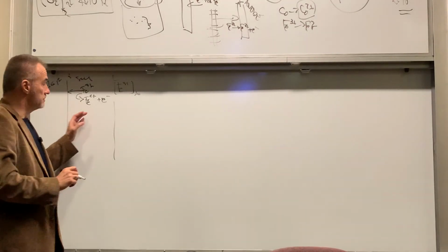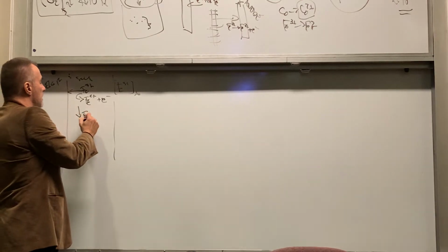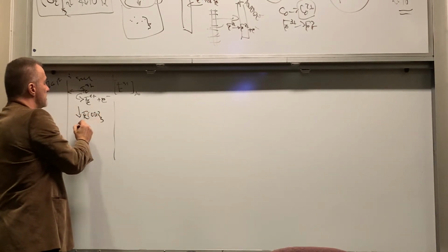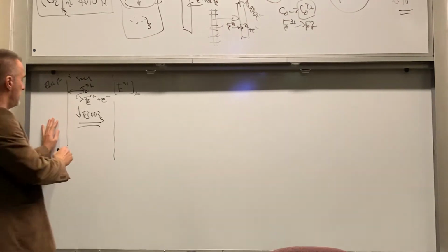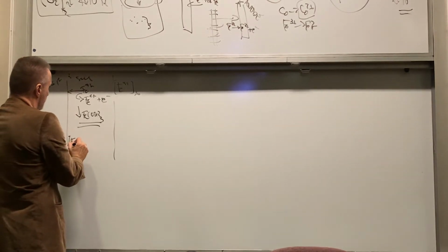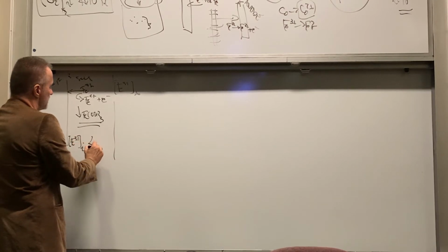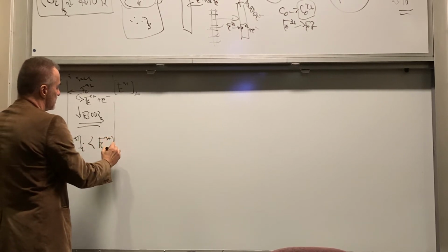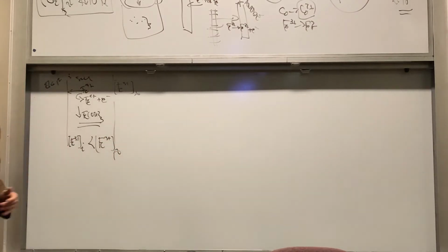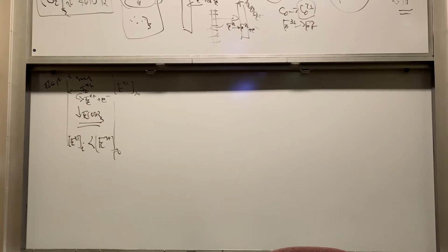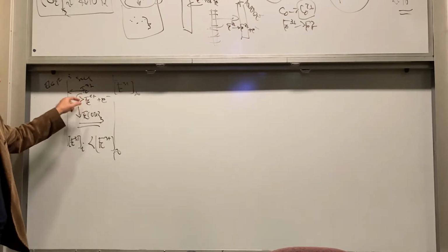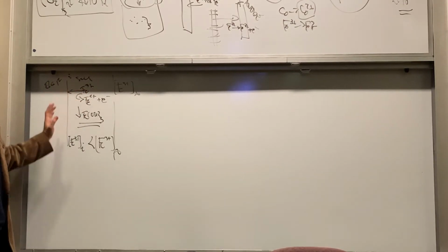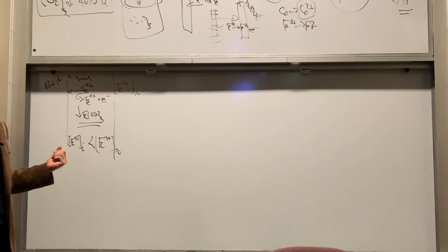Part of iron 3 is trapped in FeOH3 precipitate, right? So definitely the iron 3 concentration at the interface should be smaller than the iron 3 plus concentration in the bulk. Am I right? We should expect some depletion because we are precipitating iron 3 hydroxide, plus there will be some conversion into iron 2 at the negative potential, the cathodic process that we do in electrodeposition.